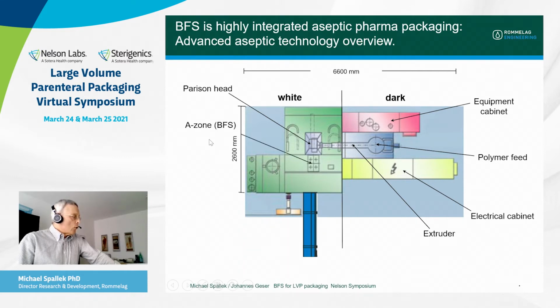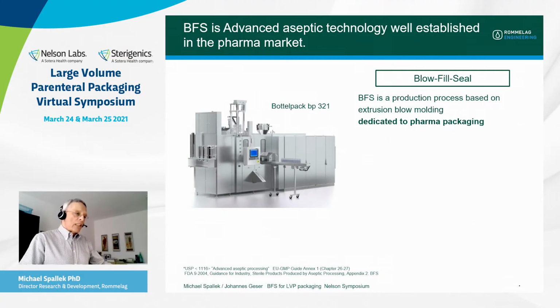Then at the A zone, you do the blowing and filling steps and the closing. Of course, we do also have sterile filters for the formulation and for the air. And from the buffer tank, we have the formulation transferred into the container by typically time pressure dosing. The mold opens and we can transfer the containers into the next steps. A machine looks like that. This is an example of a bottelpack 321 machine.